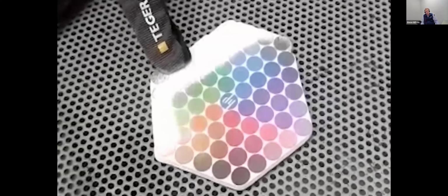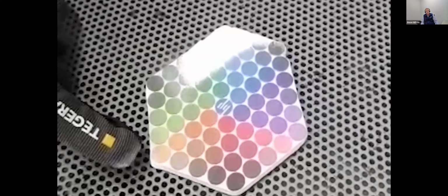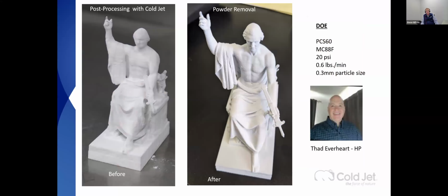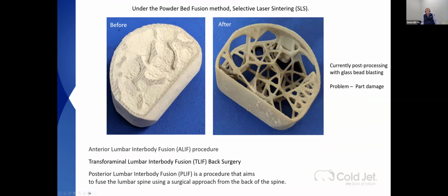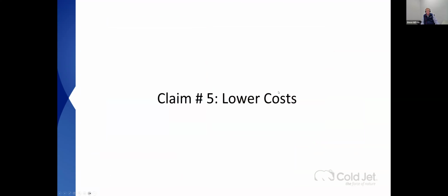So if you're doing some 3D printing, you can look at dry ice as a way to do some post-processing. You can see these particular parts sent in by Hewlett Packard. You can see some very delicate features on this particular part, where powder was removed without damaging those delicate features. This is the before and after for an SLS printed part for powder bed fusion post-processing, getting rid of the powders without damaging all these integral structures.